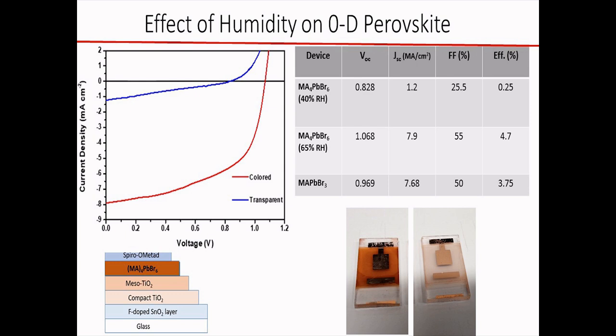So we made some devices using this 0-dimensional perovskite, and we could actually obtain efficiencies much better than the 3-dimensional MAPbBr3 that is present, and we could get efficiencies close to 5% efficiency at 65% RH. At low humid conditions, the film is something that is transparent, that looks like this, but under high humid conditions, it turns to something that is colored, and then we get the photovoltaic efficiencies.